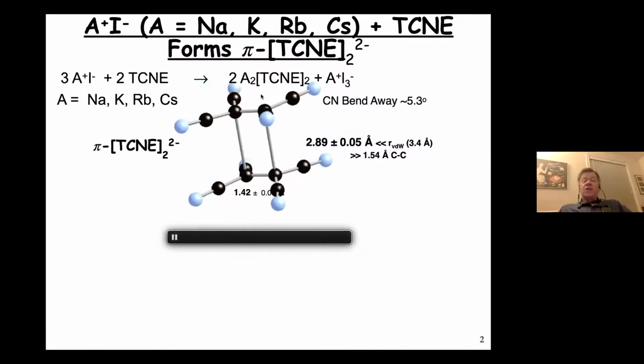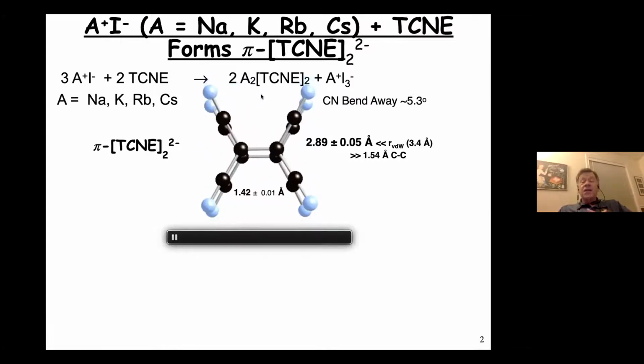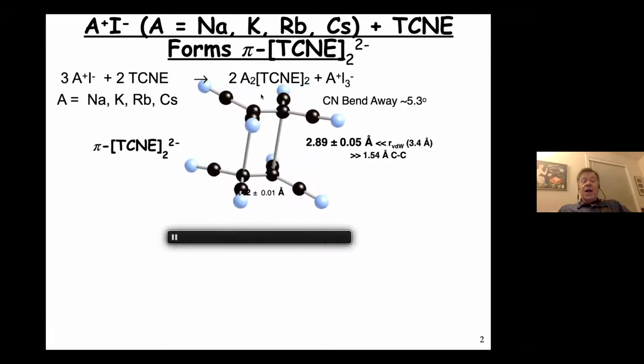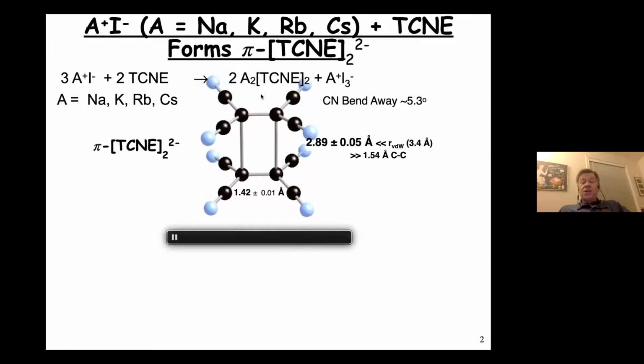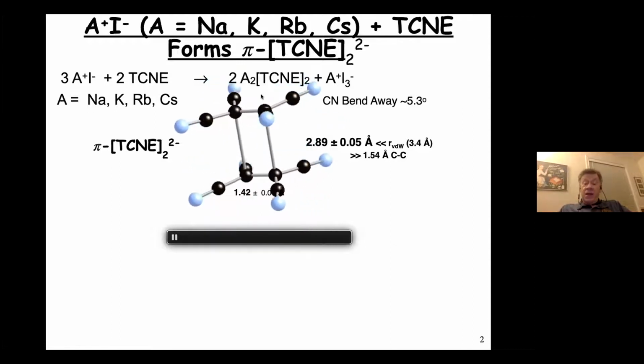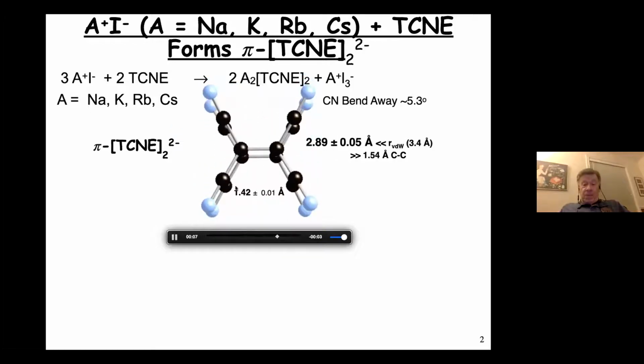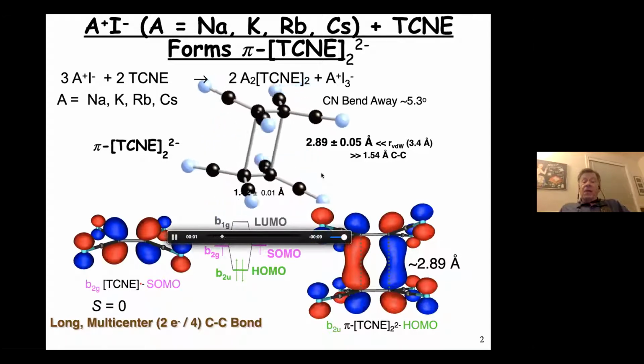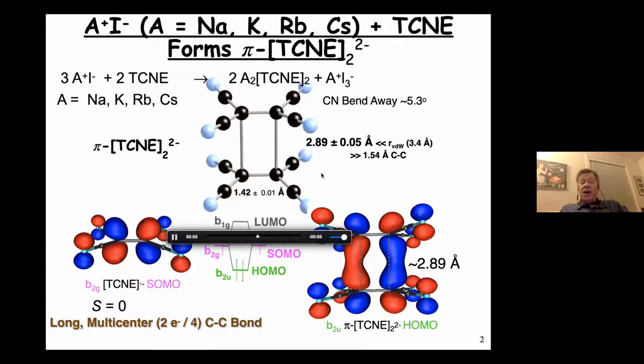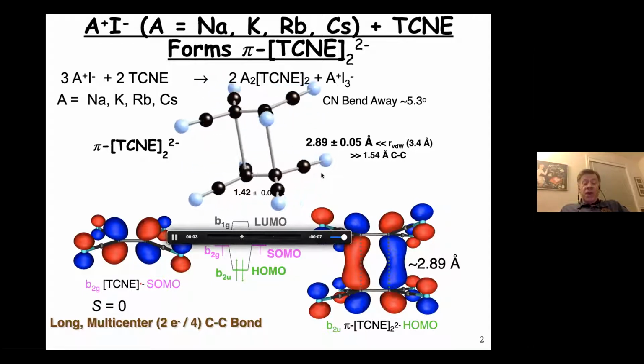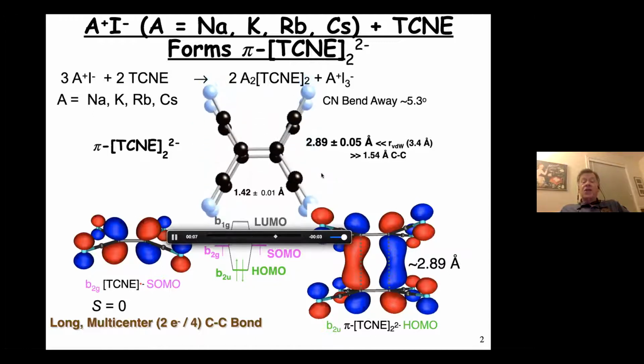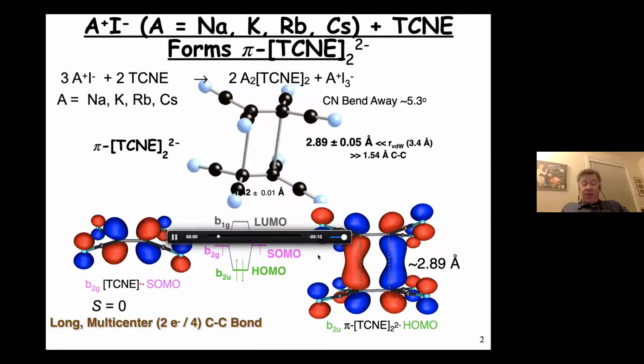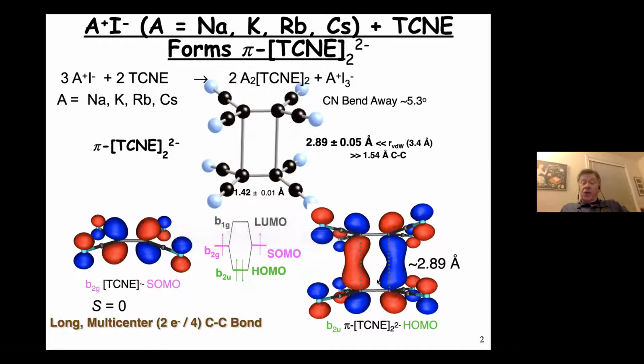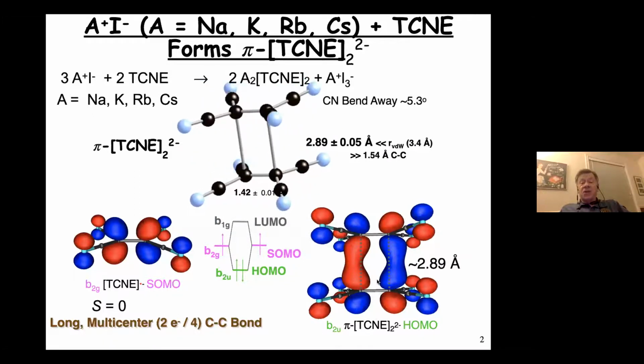First thing I want to talk about is that the reaction of alkali metal iodide with TCNE reduces TCNE to make a radical anion. If you react it with sodium, potassium, rubidium, and cesium, you end up forming a compound that has a 2- dimer of TCNE, which is a very unusual species. This compound has a very unusual, very long carbon-carbon bond of approximately 2.9 angstroms, and is created by the overlap of the B2g singly occupied molecular orbital on each of the two fragments to give what we have on the bottom here, a 2-electron 4-centered bond. So it's a very unusual species from an organic chemistry point of view.